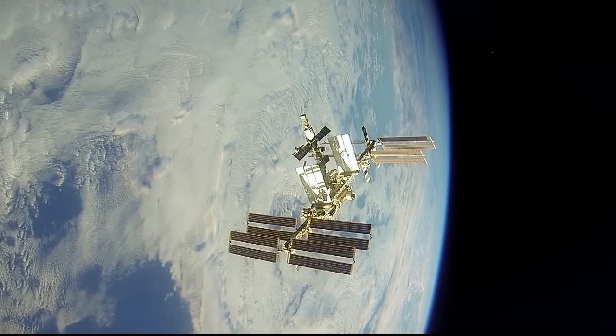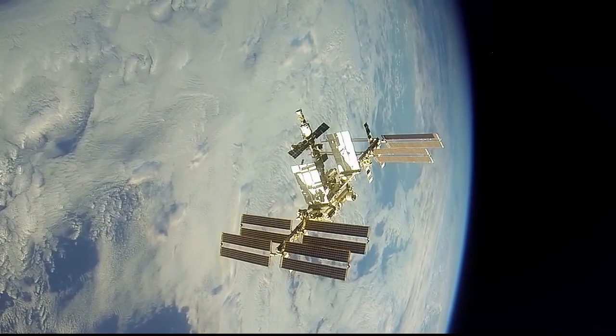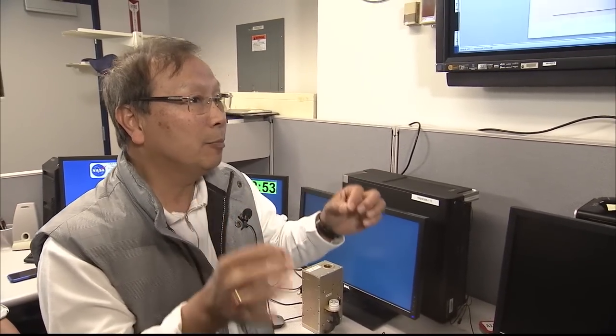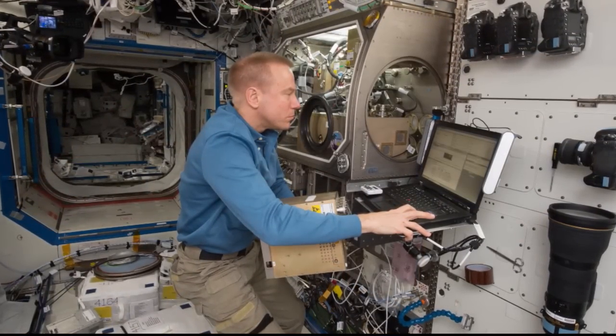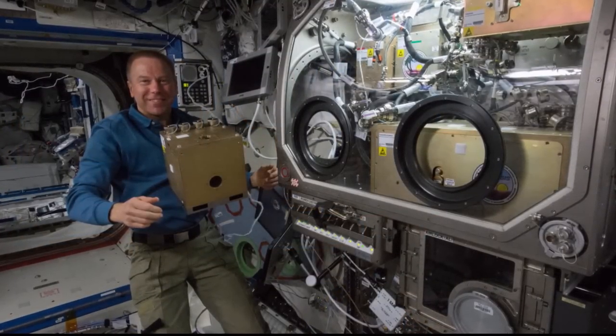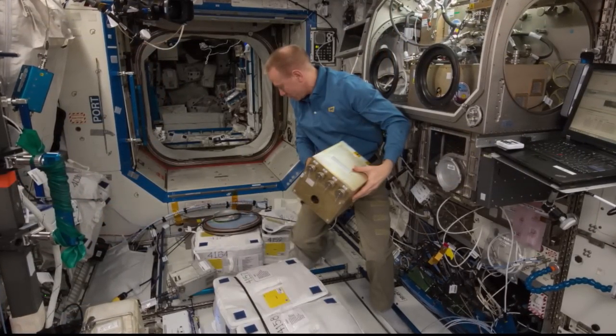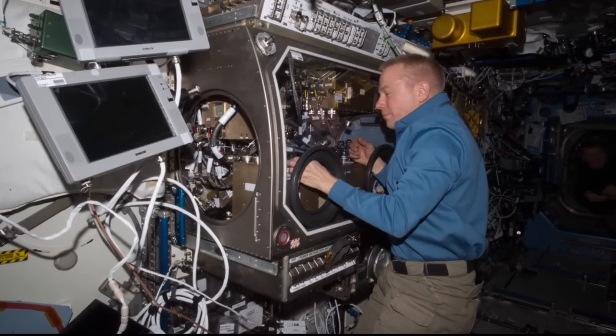The space station is an ideal place for that — microgravity. You're able to grow or make a very thin film, say about three or four layers, which is about 10 nanometers thin, and look at how the little islands or defects grow or coarsen. The best place to study this is the International Space Station because it's convection-free and has no gravitational effect. When there's no gravitational effect, other dominant features like surface tension come into play, giving us the advantage of looking at how these little defects grow and interact.